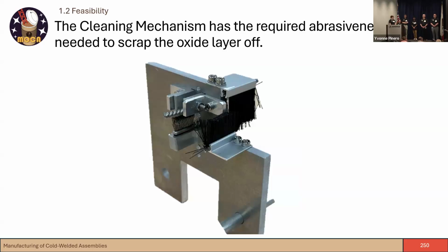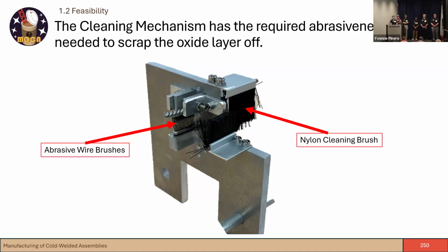So to actually remove the oxide layer, you can see the cleaning mechanism up on the screen. We use abrasive wire brushes to scrape the oxide layer off of the aluminum members. And the nylon cleaning brush then removes all of that scraped off oxide layer and prevents any of that debris from staying on the clean surface.